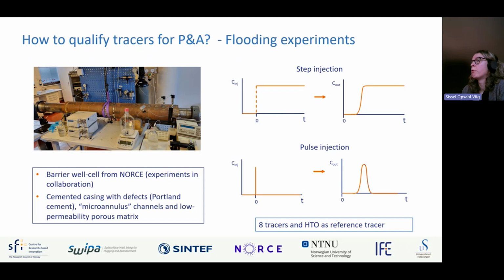And then we move forward to the second type of experiments that we perform, which is flooding experiments. To perform these experiments, we were lucky to borrow a cell from one of our research partners in NORCE, and you see a picture of it here. It's a barrier cell with a cemented casing with some defects. The cement is Portland cement, and it has some microannular channels and a low permeability porous matrix.